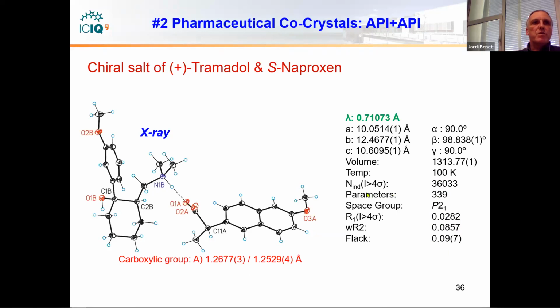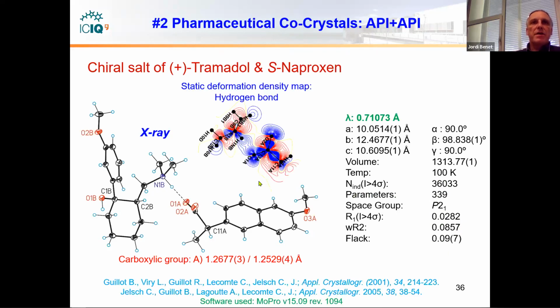And so with this we could do a structural study using charge density, so that we could get static deformation density maps of, for example, this hydrogen bond. In comparison to this, we could analyze a bit better the different hydrogen bridges which we have here. Here is one, but also there we have hydrogen bonds and contacts. We try to make a study of this and understand when we have a good crystal and when we have a solid.